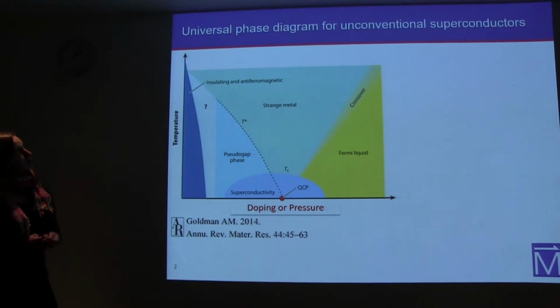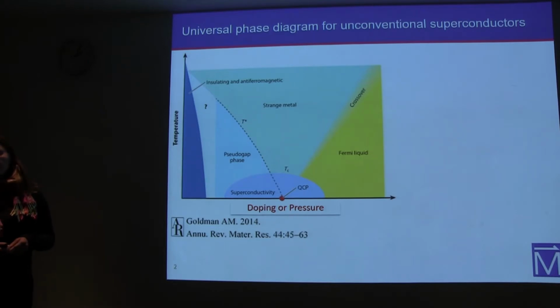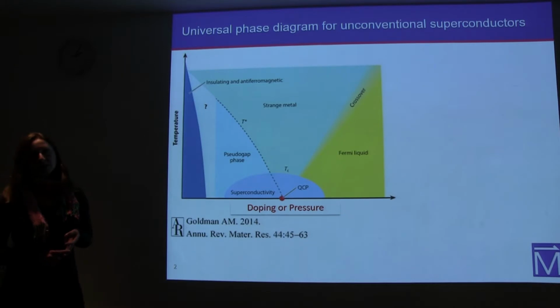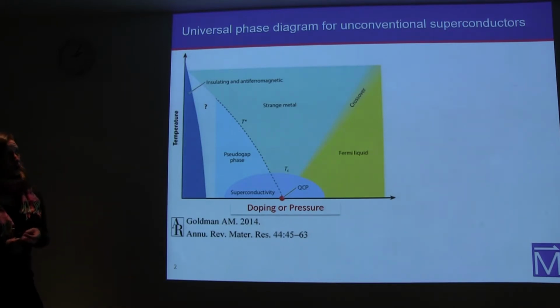So I would like to start by reminding you of the unconventional superconductors. Unconventional superconductors cannot be described by the standard BCS theory. Some families, cuprates, but also heavy fermions, cerium-based compounds, uranium compounds, or also organic superconductors, actually all fall on the same phase diagram, the so-called now universal phase diagram for unconventional superconductors. In this phase diagram, where I show temperature versus a tuning parameter that can be either doping or pressure for that compound, all those unconventional superconductors share similar characteristics.